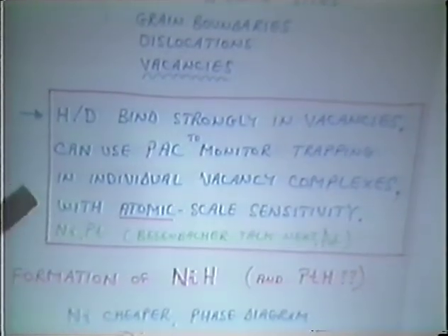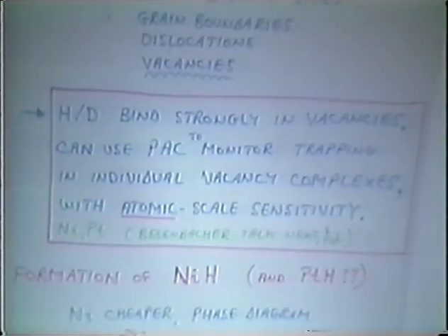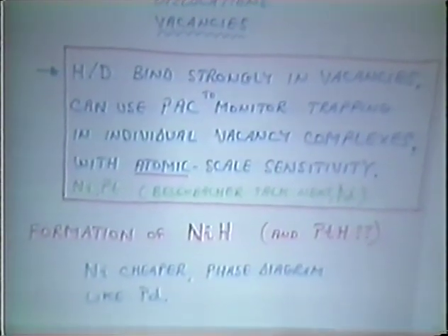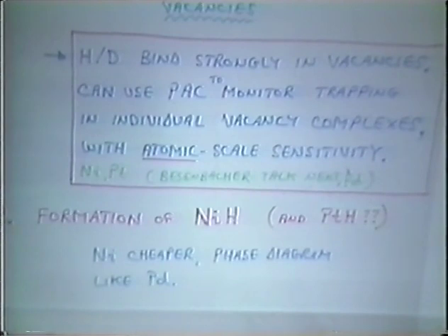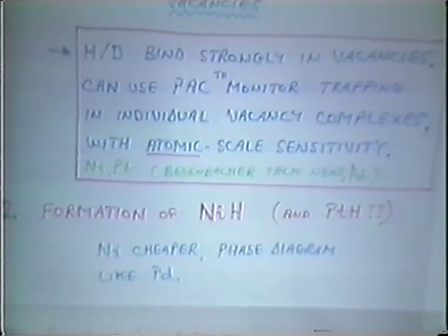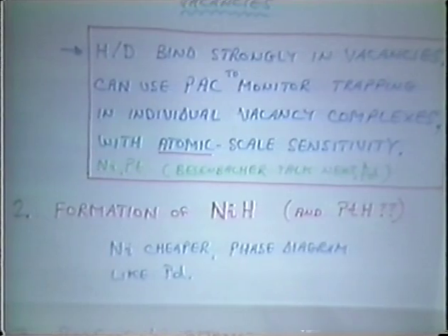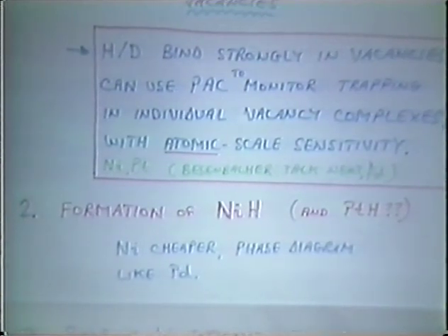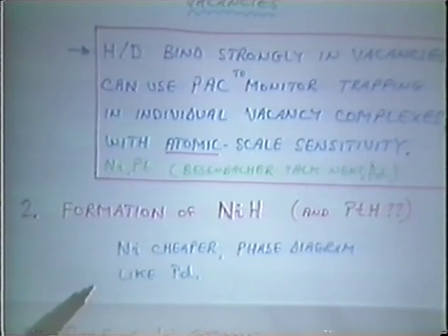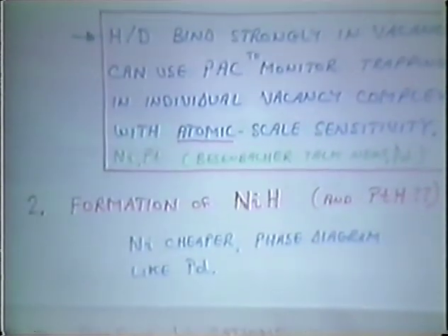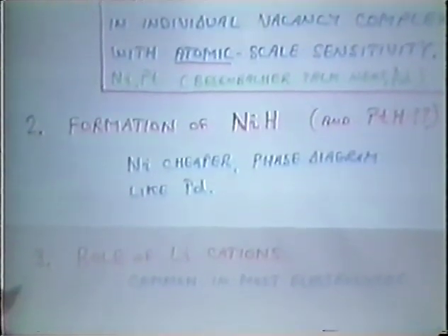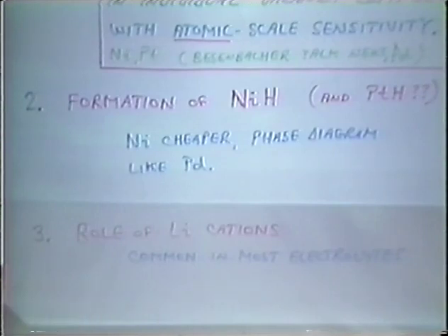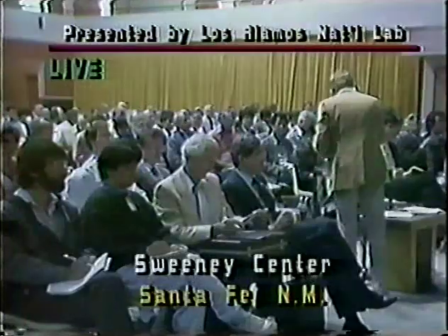So I'll be telling you about hydrogen trapping in vacancies, about formation of nickel hydride, which we believe we've seen in the past, and even potentially palladium hydride. Of course, nickel, palladium, and platinum are in the same column in the periodic table, and nickel is a lot cheaper, and its hydrogen metal phase diagram is similar to palladium. And then we've done some very recent measurements on the role of lithium cations, which of course were a common cation in almost all the electrolytes which people have used. Okay.